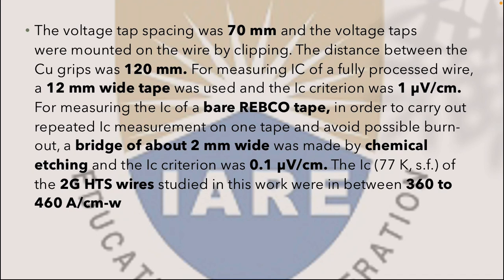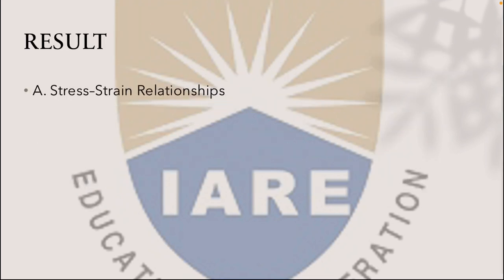For measuring the Ic of bare REBCO tape, in order to carry out repeated Ic measurements on one tape and avoid possible burnout, a bridge of about 2 mm wide was made by chemical etching and the Ic criterion was 0.1 μV per centimeter. The Ic of the 2G HTS wires studied in this work were between 360 and 460 amperes per centimeter of width.